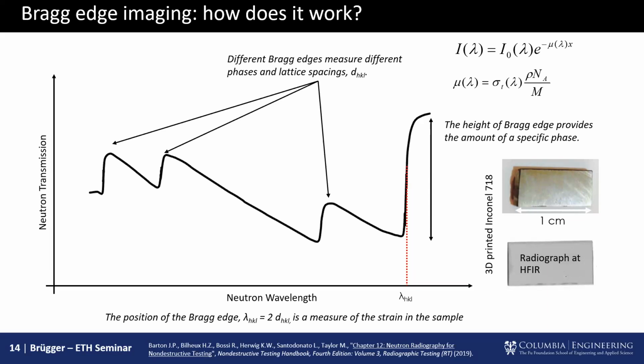So what we can do now, instead of just looking at, for example, a single energy radiograph, if I do that, then I will see, you don't see my pointer, you'll see this radiograph here of this block that was 3D printed. Looks like metal, right? But now if I do a hyperspectral radiograph where I'm actually measuring and discriminating the energies of the entire bandwidth of the neutrons that I'm receiving, so it's equivalent to a color camera versus a black and white camera, right?